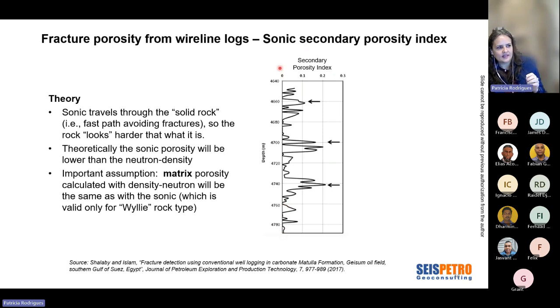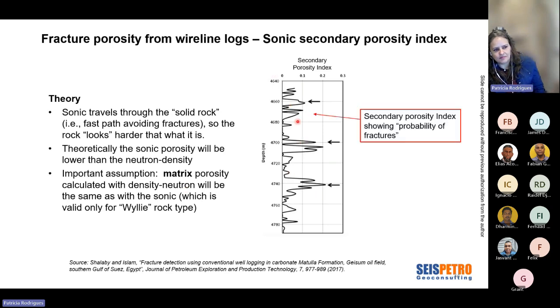This porosity index is the difference between the neutron density porosity and the sonic porosity. And this secondary porosity index can show you the probability of fractures if you know there is no vuggy porosity or anything. The thing is that the assumption here is, I would call it, too strong. There are only a few cases when you're working in fractured reservoirs where this assumption is really valid. So even though you can use the secondary porosity index as an indication, it is not a quantitative way of measuring how much porosity from fractures you have.